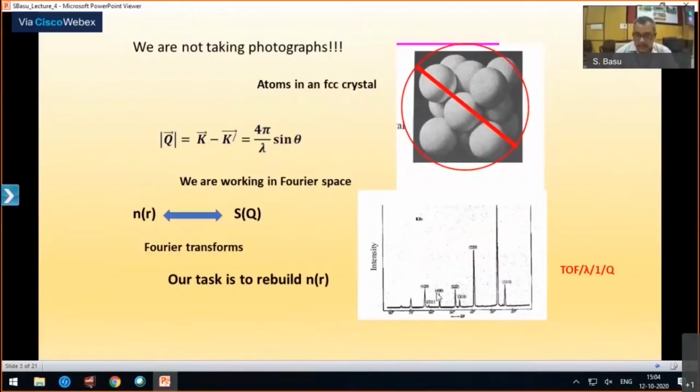Now, I specifically show this data because it is very interesting. You can see that the peak intensities are increasing with respect to the x-axis. Generally, you are not used to seeing intensity data in Bragg scattering like this. It's the other way around. I showed you this because this is time of flight data from an accelerator-based source, and time of flight goes with respect to lambda.